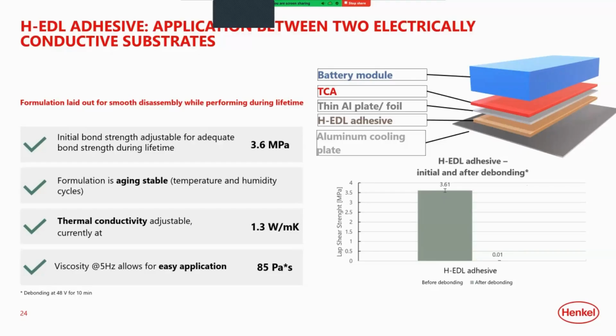The adhesive basically comes in 2 forms, either a thermally conductive adhesive version or a purely structural version. For the thermally conductive version, we're reaching strengths of around 3.6 MPa, but we're achieving strengths up to about 10 to 12 for the purely structural material. You can see the before versus after debond comparison of lap shear strength on the graph at the bottom right, where that 3.6 MPa in use strength for the thermally conductive material reduces to virtually 0 after the voltage is applied.